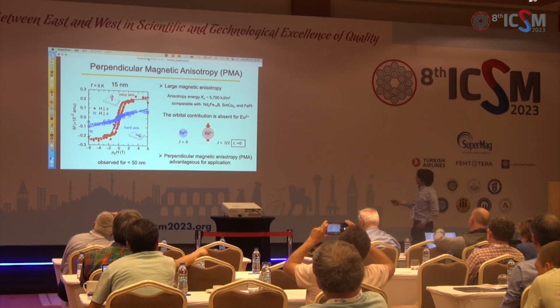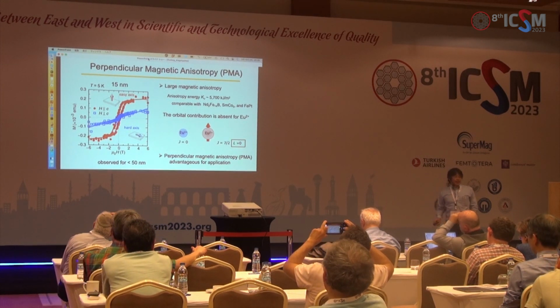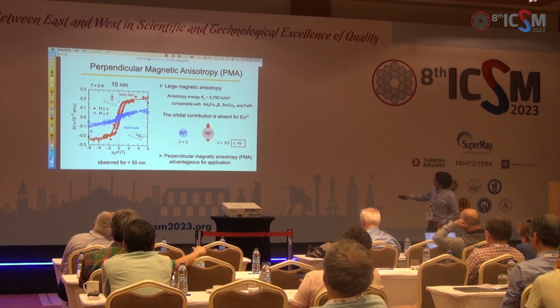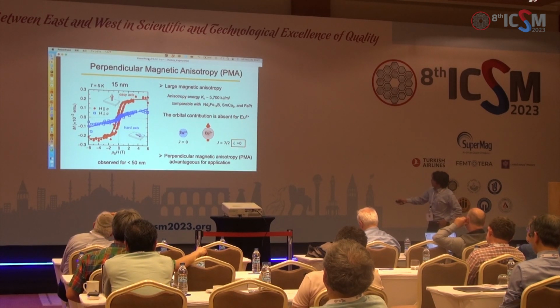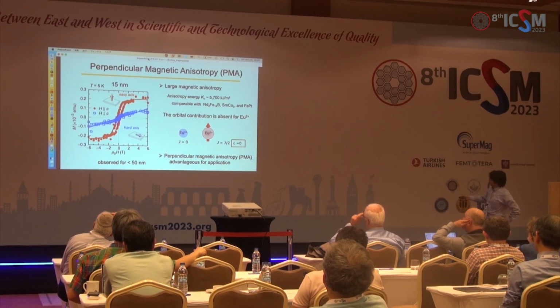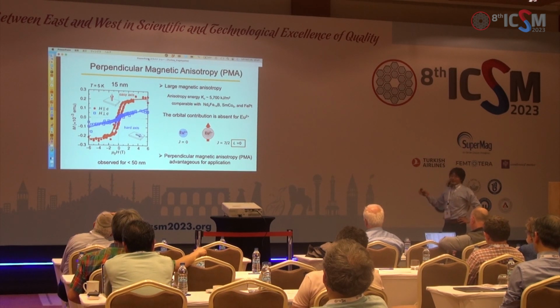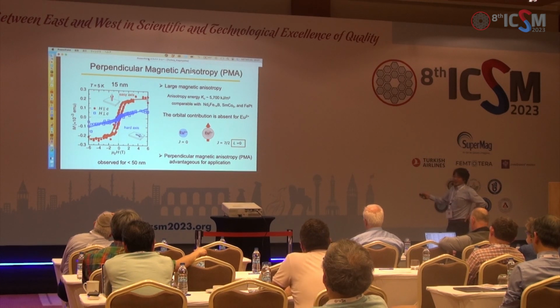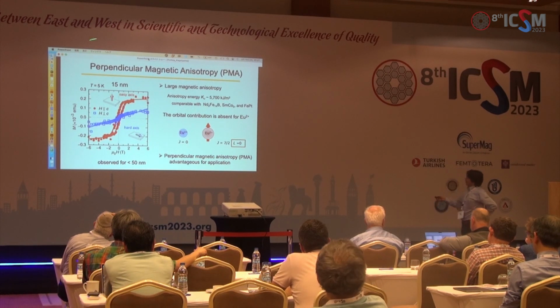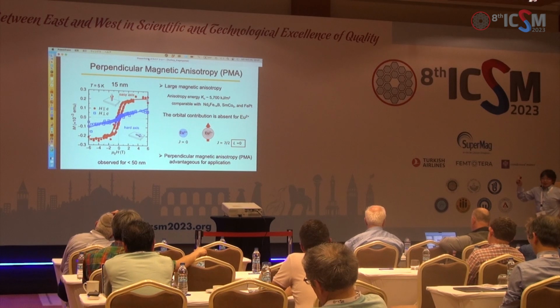Another observation is that the magnetic anisotropy is relatively large. This is the magnetization along the easy axis, and this is the magnetization along the hard axis. So you can see that the anisotropy is very large. But when you consider Eu2+, it doesn't carry orbital momentum, it's L equals 0, so the moment comes from the spin only. Nevertheless, we observe such a high magnetic anisotropy. And considering potential applications, perpendicular magnetic anisotropy is also interesting. But anyway, we observe such a large magnetic anisotropy in these materials. Actually, this doesn't occur in the powder samples, so maybe this is another interesting feature.